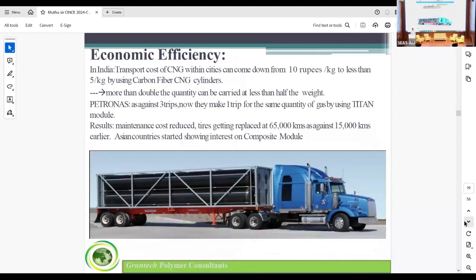You can see this is a huge Titan tank from Hexagon Purus. In India, the transport cost of CNG within cities can come down from 10 rupees per kg to less than 5 rupees per kg by using carbon fiber CNG tanks. More than double the quantity can be carried at less than half the weight. Petronas in Malaysia, as against 3 trips earlier, now makes one trip for the same quantity of gas using the Titan model. You can see the comparison with metal cylinders and Type 4 composite cylinders. As a result, Asian countries have started showing interest in the composite model.